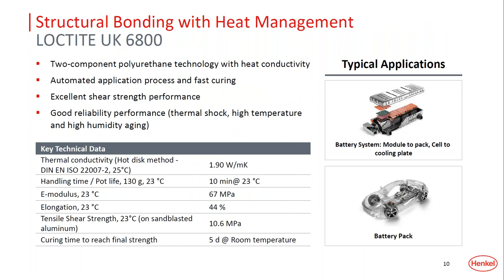So, structural bonding with heat management. Loctite UK 6800 is a two-component polyurethane adhesive. Typical customer recommendations are around 1 watt per meter K when it comes to thermally conductive adhesives. UK 6800 offers almost double that, with 1.9 watts per meter K. Pretty impressive for a structural adhesive.